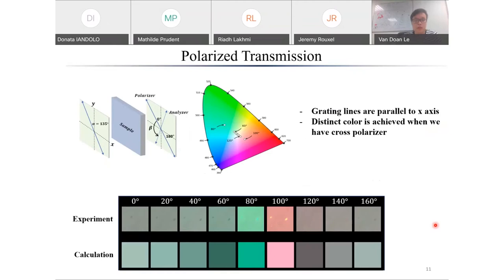So here's the result of the polarized transmission. I put the sample sandwiched between one polarizer and one analyzer. The first one here represents the direction of the polarizer, and this is the direction of the analyzer. So beta is the angle between the analyzer and polarizer. You can see the color here represents the spectrum due to the variation of beta and the angle of the polarizer, and we can achieve various colors in this case. The really distinct colors appear when we mostly have crossed polarizers. This is an indication of the phase retardation of the sample, or in other words, the anisotropic property of the sample.